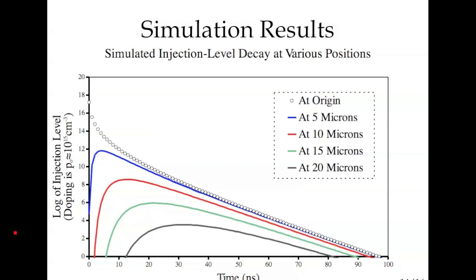If we're looking at these curves, it would be very hard to get the lifetime without modeling diffusion. And we can see that the time that it takes to reach homogeneity actually gets longer and longer. So here I'm still, if I tried to measure tau, I'd still get infinite. So I'm not measuring tau until much later times as I move further away.